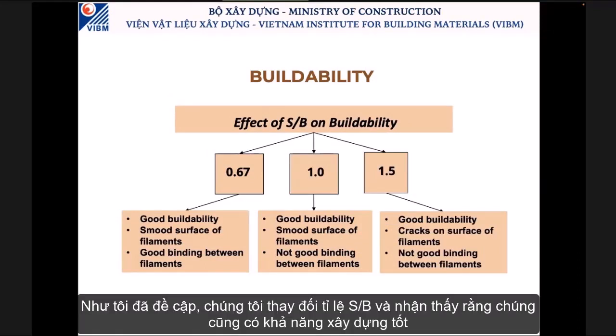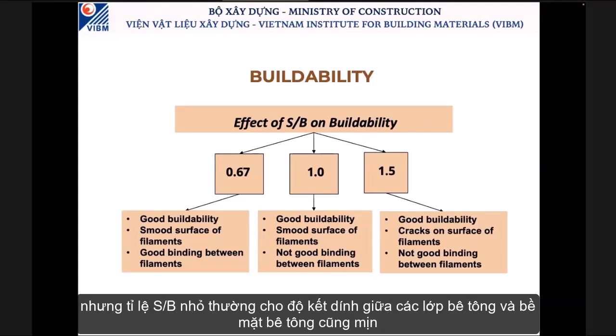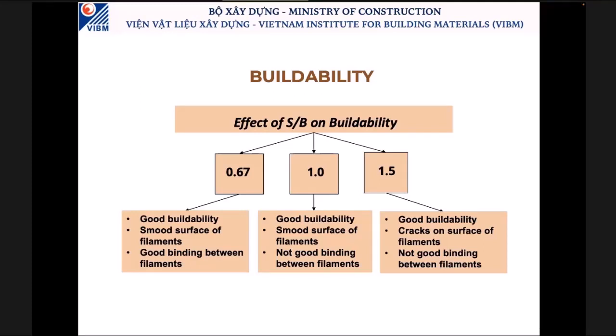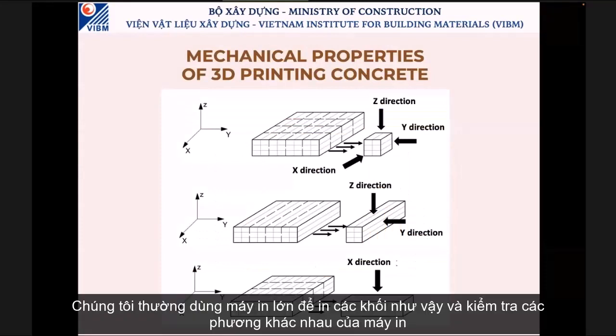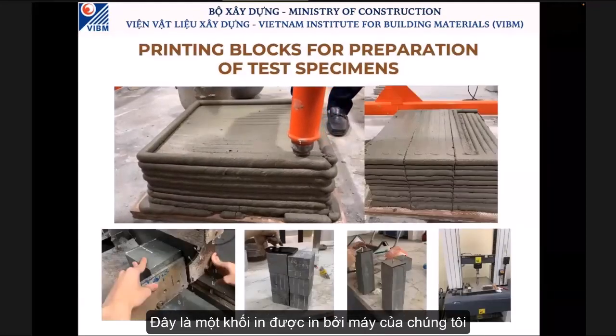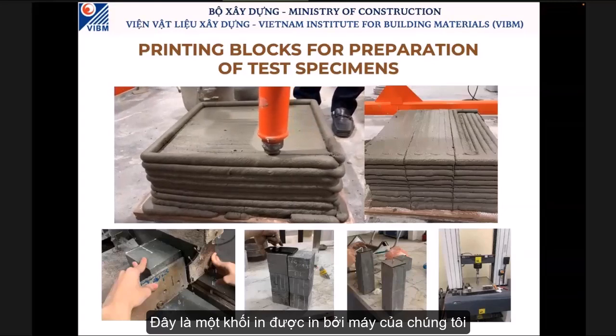And also, as I mentioned, we vary the ratio of the sand and binder, and we also found that they have quite good buildability, but a lower sand binder ratio has a good binding between filaments and a smooth surface of filament. So we use the big printer for printing a number of blocks like that to test different directions of the concrete printing. Here is one of the blocks we print using our printer.